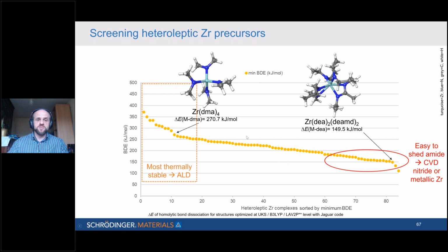And here are 2 examples from each of those classes. And I think we wouldn't have predicted that these were some of the best molecules in the set. So the tetrakis dimethylamide is a really good candidate for ALD, and changing it, adding 2 amidinates and a diethylamide, turns it into a good possibility for CVD. So a really big difference in bond dissociation energies.